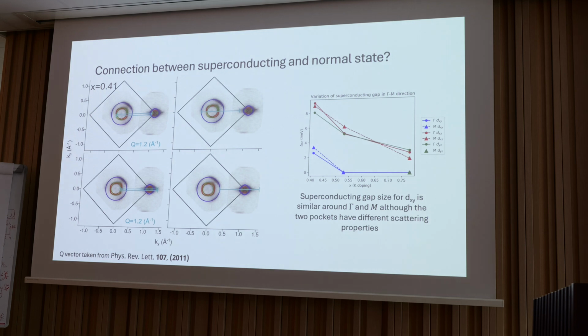So now we can ask, is there any connection between the superconducting and normal state? I'll try to make some naive arguments. Taking the Q vector from the neutron scattering paper we saw before, we can overlay that on the experimentally determined Fermi surfaces. Take this with a grain of salt, as the Q vector is fairly broad, but when we overlay it, we see fairly good nesting between the XZ, YZ hole pockets and the electron pockets, and that's true for both the XZ and XY electron pockets. Whereas the outermost XY hole band is very poorly connected to any of these electron pockets around M.